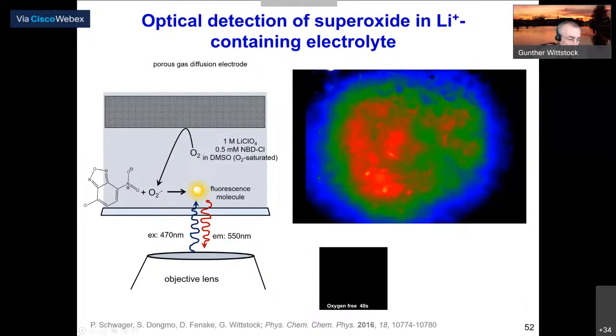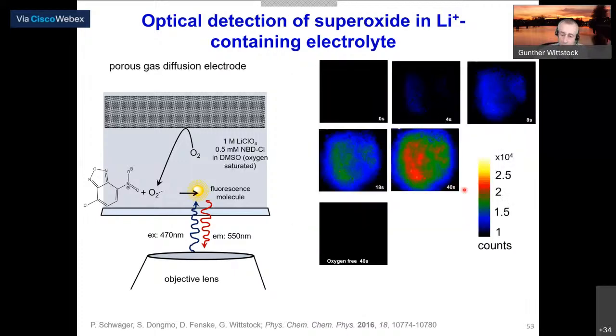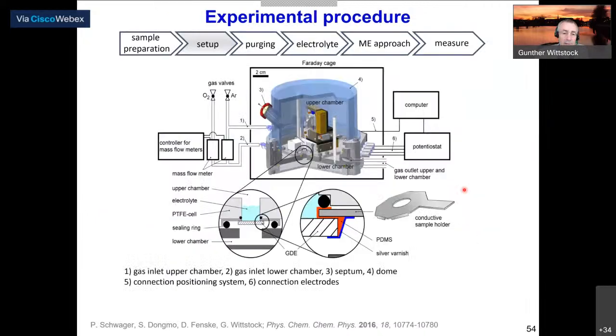If we make a control experiment here, then after 40 seconds, we see nothing. The control experiment is done in the absence of oxygen. So you see first that a lot of this is formed, that the formation is inhomogeneous over that electrode. And so there are lots of things which are going on beside the reaction, which is just written down for the textbook. So here once more.